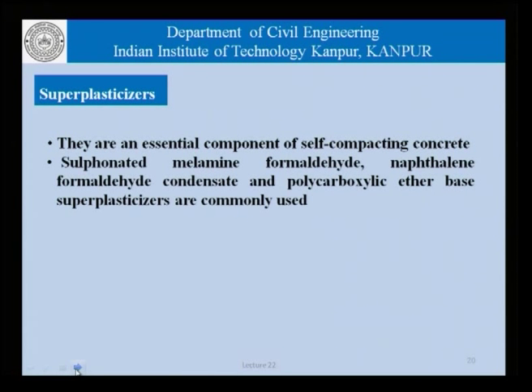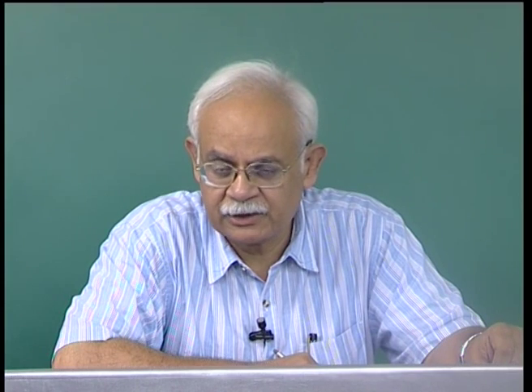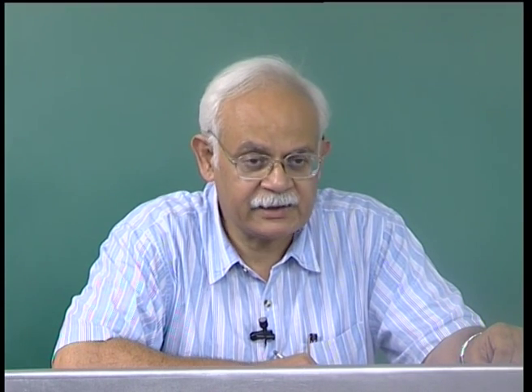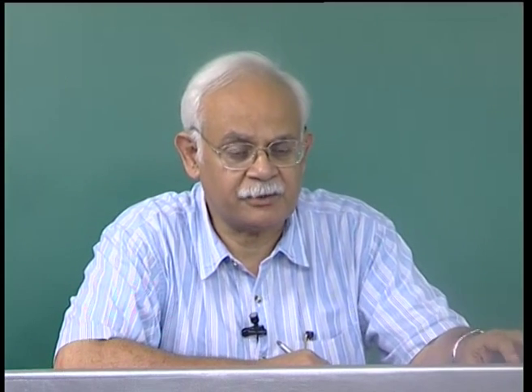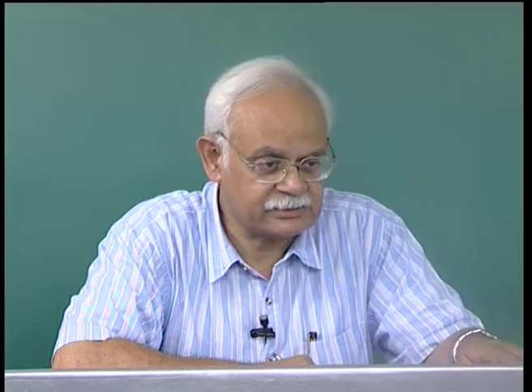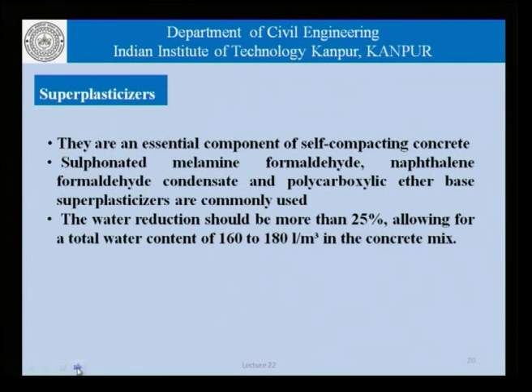Coming to superplasticizers, they are an essential component of self-compacting concrete because they help us reduce the water content. And as far as these admixtures are concerned, normal sulfonated melamine formaldehyde, naphthalene formaldehyde condensate, and polycarboxylic ether-based superplasticizers are commonly used. Depending on the chemical composition of the cement, there may be issues relating to compatibility of a particular admixture with the cement and so on. And that is something which needs to be established from time to time as far as a construction site is concerned.